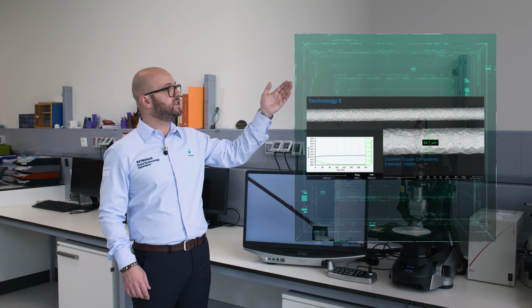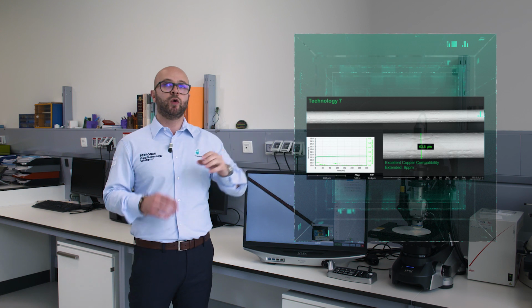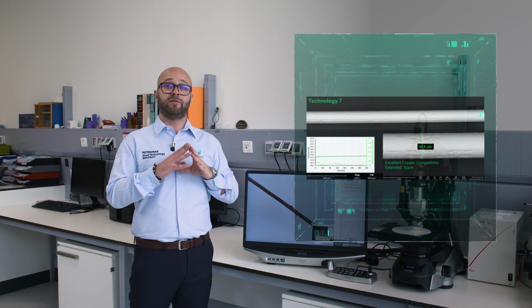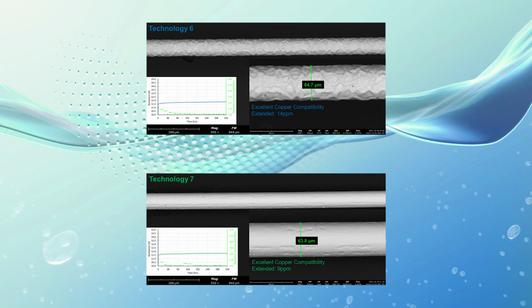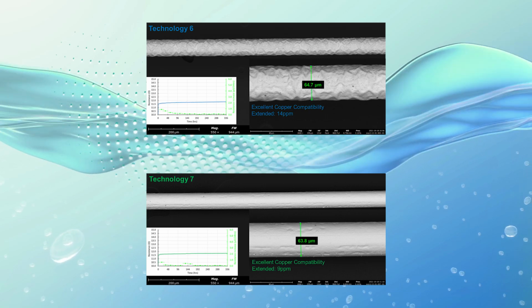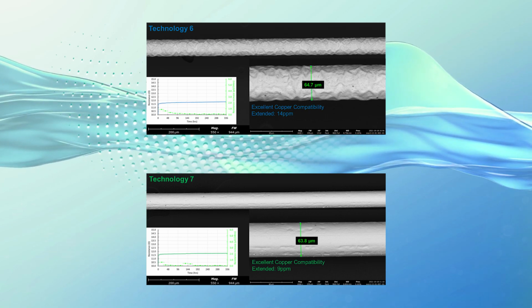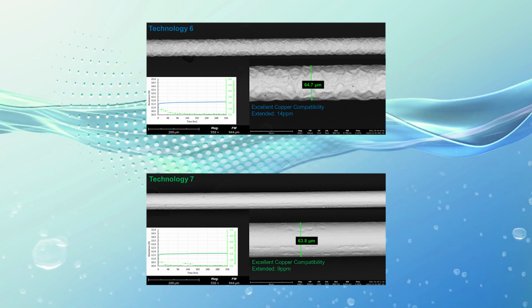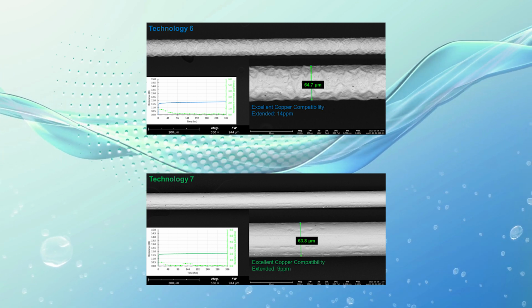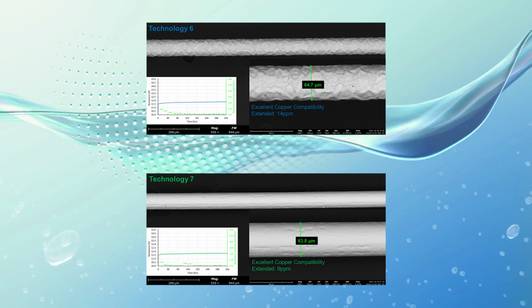When we move to technology 6 and 7, which were showing excellent corrosion protection, the situation is completely different. In both technology 6 and technology 7, we have a surface that is very clean without any precipitation of corrosion product, at least at a macroscopic level. The difference between technology 6 and 7 is that in technology 6 we have a localized attack on the surface visible in several points of the wire.